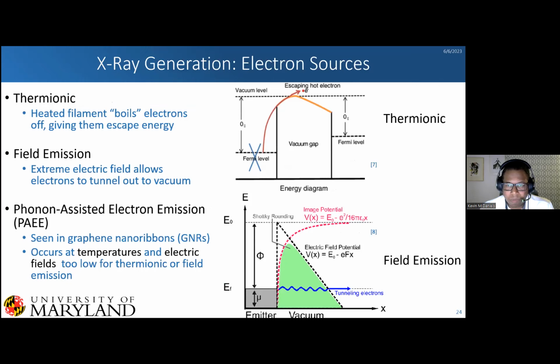What sent us down this path with graphene was a phenomenon called phonon-assisted electron emission, where people have seen in suspended graphene nanoribbons that you can get electron emission at temperatures and electric fields far too low for either thermionic or field emission. Most electron emission we can think of is thermionic, where you have, let's say, a tungsten filament, heating it up to a couple of thousand Kelvin, really boiling off electrons and giving them the energy to escape, essentially surmounting the vacuum gap and hitting the vacuum level.